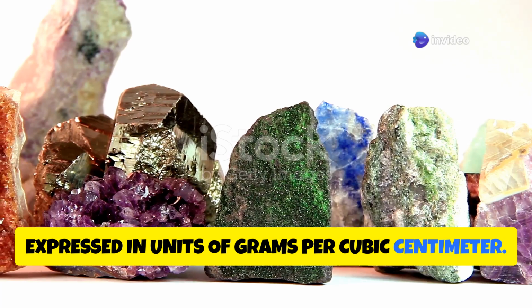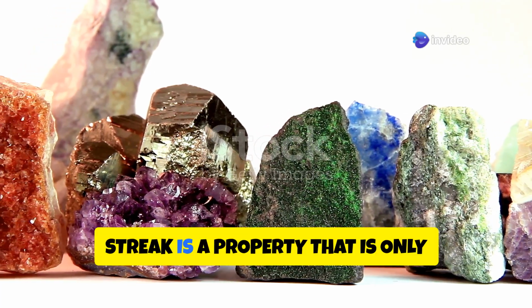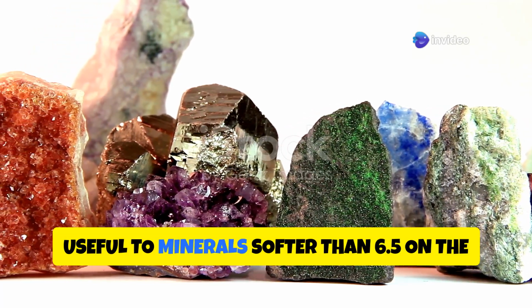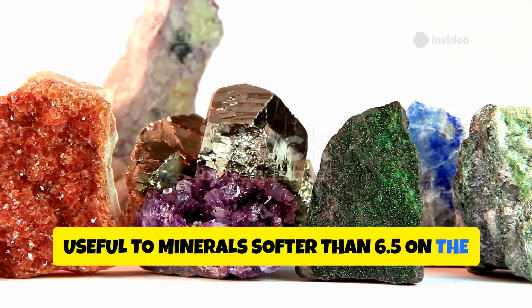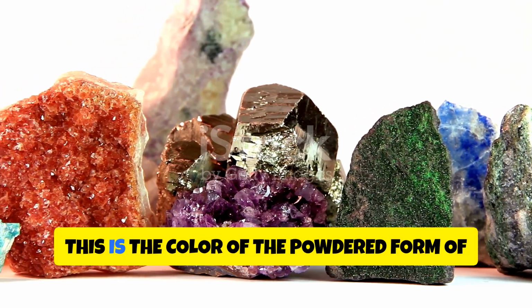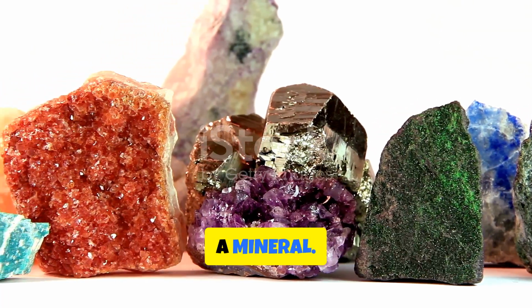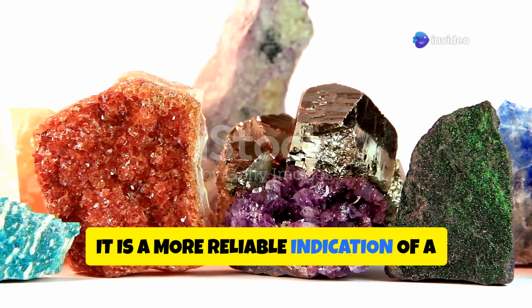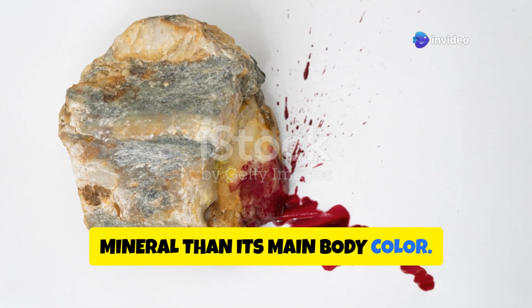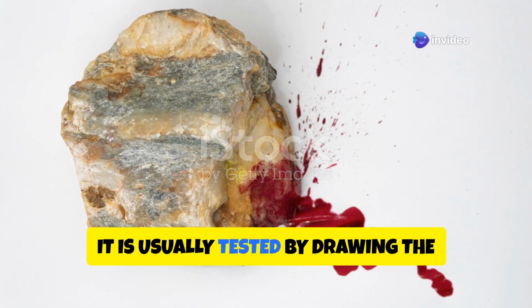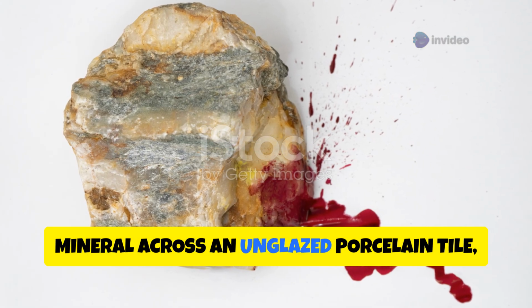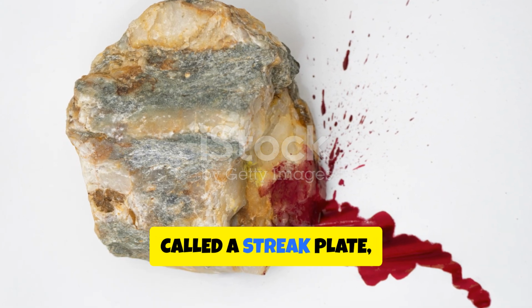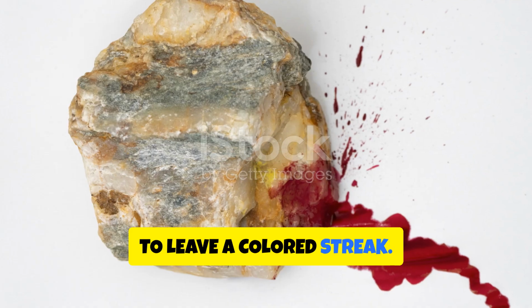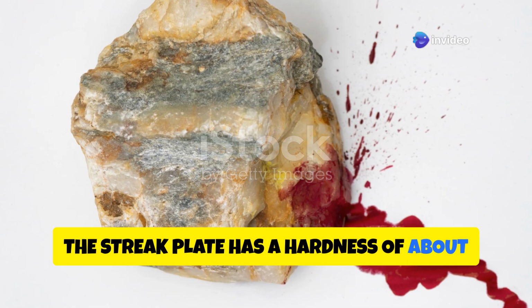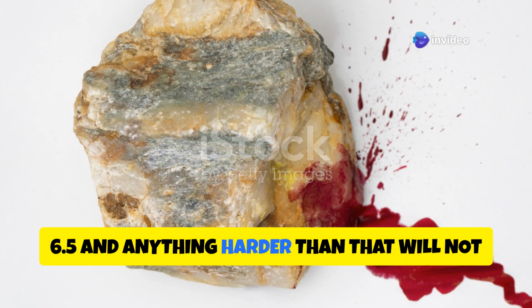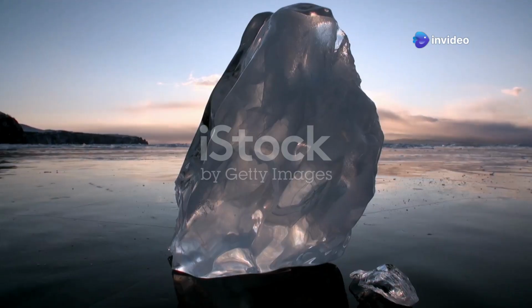Streak is a property that is only useful to minerals softer than 6.5 on the Mohs hardness scale. This is the color of the powdered form of a mineral. It is a more reliable indication of a mineral than its main body color. It is usually tested by drawing the mineral across an unglazed porcelain tile, called a streak plate, to leave a colored streak. The streak plate has a hardness of about 6.5, and anything harder than that will not leave a streak.